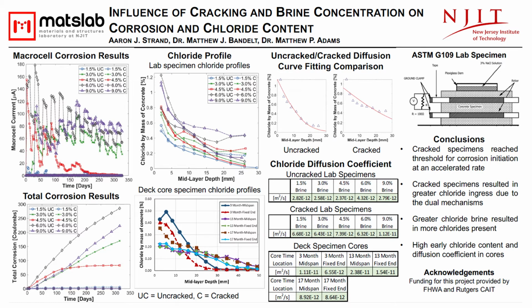From the macrocell corrosion results, the 10 microamp current threshold was reached for all cracked specimens, though the threshold was not consistently exceeded for the specimens ponded with 1.5 and 4.5% brine by the end of testing. For the cracked specimens ponded with 3% brine or higher, the threshold was reached within the first 2 ponding cycles. Though at 4.5% brine, the macrocell current dropped below the threshold after 7 cycles.